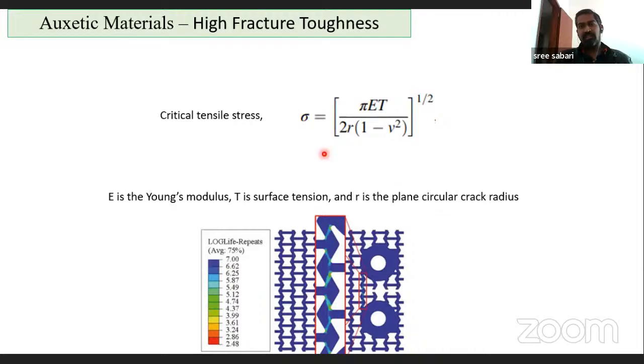So here you can see there is a critical tensile stress. There is a critical stress that needs to be created in order to propagate a crack. Okay, so this has a relationship with the Poisson ratio. If the Poisson ratio is related with the critical stress, of course, we can tailor the Poisson ratio to negative and we can increase the resistance against the fracture.